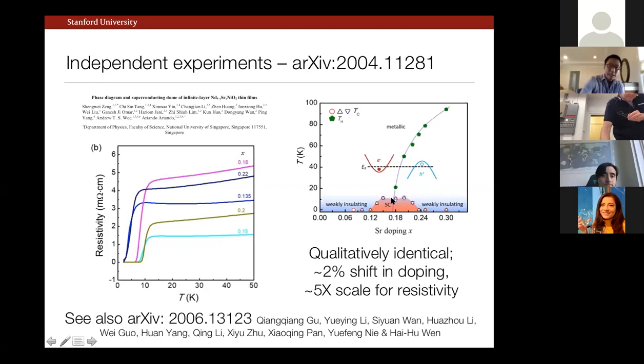And what is actually amazing to me is despite the tremendous difficulties we have in stabilizing these materials, these two papers are qualitatively quite similar. So at most, there's something like a 2% shift in doping of the relative position of the dome. To me, this is well within experimental, let's say, noise. One distinction is that the resistivity and the Hall coefficient scale by about a factor of 5. I can't speak for them, but certainly if they had this kind of two-phase segregation, at least it'd be self-consistent with what we had previously observed. But modulo these slight differences, it's remarkably self-similar. And also they did a nice plot here of the sign change in the Hall coefficient as a function of temperature, which they correlate with this dip in the superconducting dome.